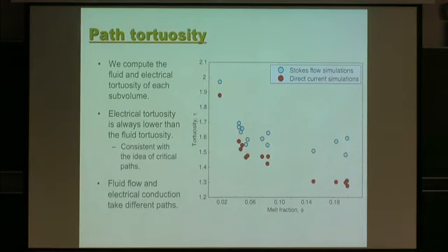That is because, remember, there's a spillover, and then you have the thin grain boundary melt, which is more prevalent in that network. So the electroconductivity is still sensitive to it, but the permeability is not sensitive to the grain boundary films. How do you quantify tortuosity here?